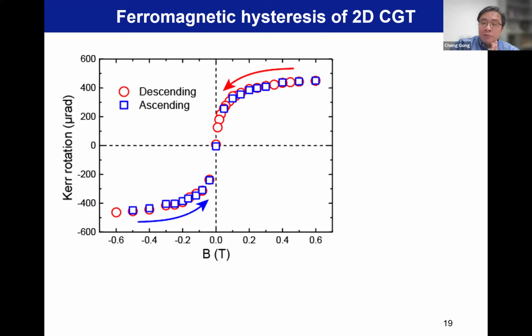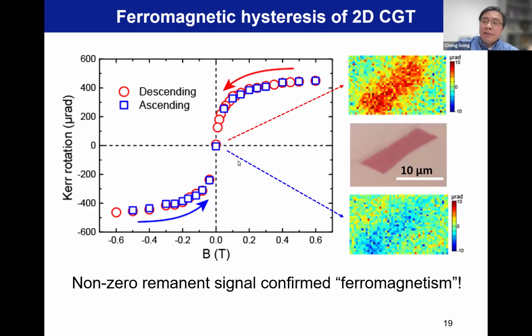You can see the hysteresis loop is pretty much like its bulk counterpart. It's a small loop, but it's still a loop. So the question is whether you have remnants or not. You can see when I withdraw the magnetic field from positive or from negative, there is a non-zero remnant, and they are opposite in sign. So again, this confirms this is a 2D ferromagnet.